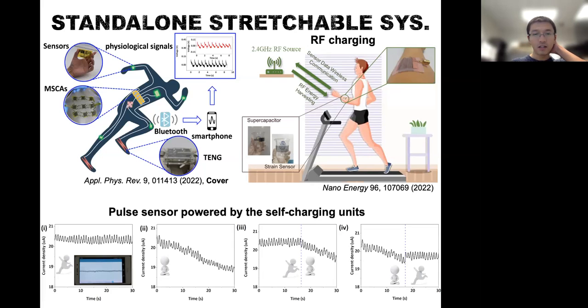On the other side, the triboelectric nanogenerator. For that one, we want to make sure the charge separation and transport from the positive to negative can be fast, and also to have a really high voltage and power output. So the porous structure of this laser-induced graphene composite is helpful here. But again, it does not need to be limited to the porous structure of the laser-induced graphene, but it can also be the others. For example, the other type of nanomaterials that are grown or synthesized from different methods can be very useful as well. It really depends on, for example, what's the particular